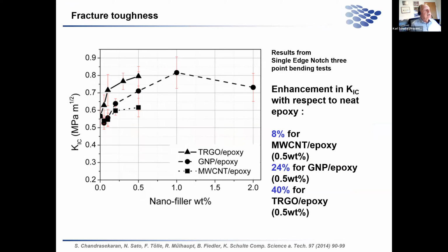I have plotted here another figure: increase of the fracture toughness, KIC values, versus the nanofiller content. We used different types of carbon nanotubes - multiple wall carbon nanotubes - but also graphene nanoplatelets and thermally reduced graphene oxide, as you can see here.